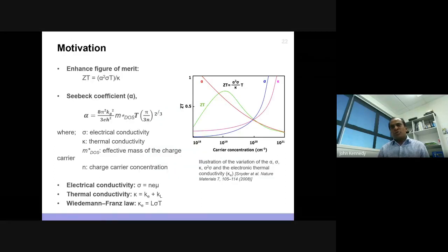So what motivated us? We, as an ion beam physics based materials science team, have been looking closely at the figure of merit and what we can do. If you look at the diagram, the carrier concentration goes straight up. I mean, alpha goes down when sigma goes up. And the thermal conductivity goes up if the carrier concentration goes up, but the alpha goes down. So you have to find a place where you can balance everything. You can optimize the carrier concentration. You can also keep alpha and sigma at a reasonable level so that your figure of merit goes up.